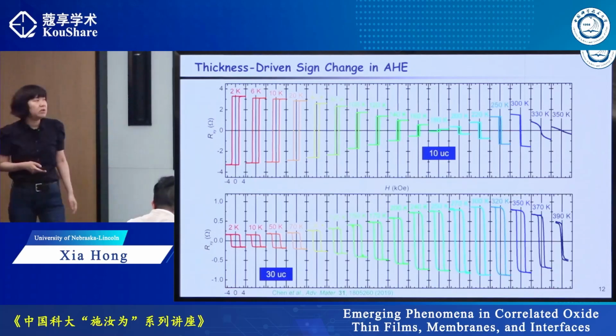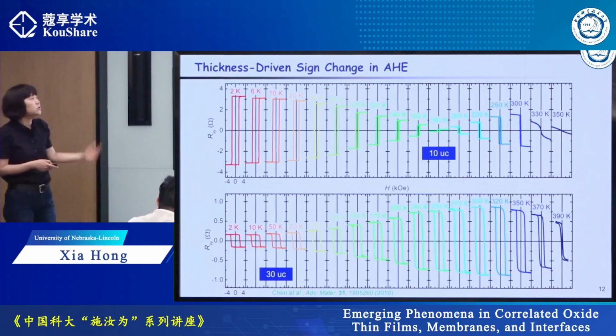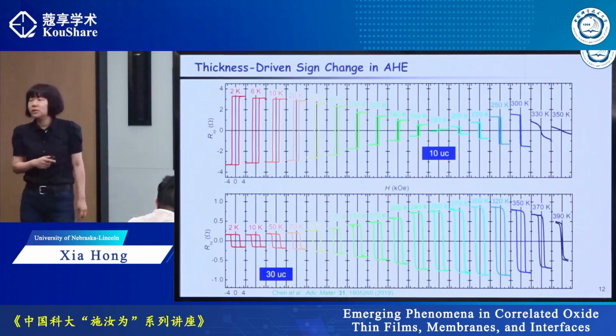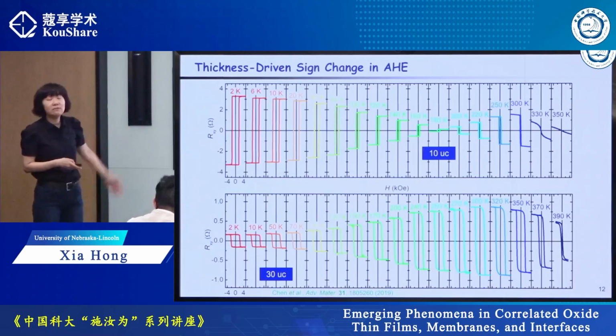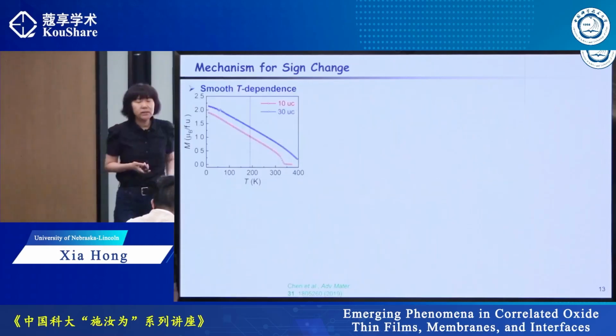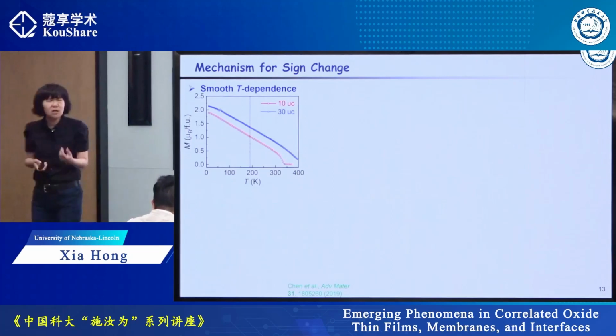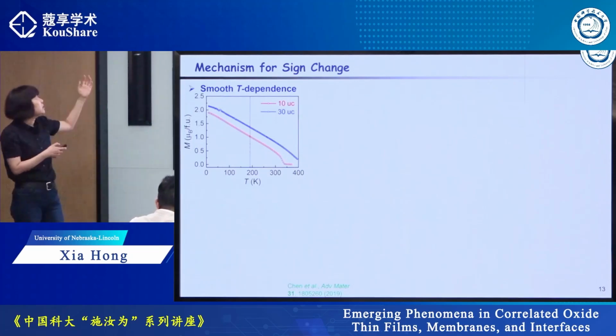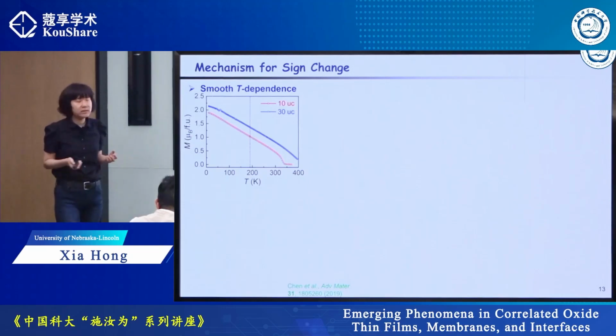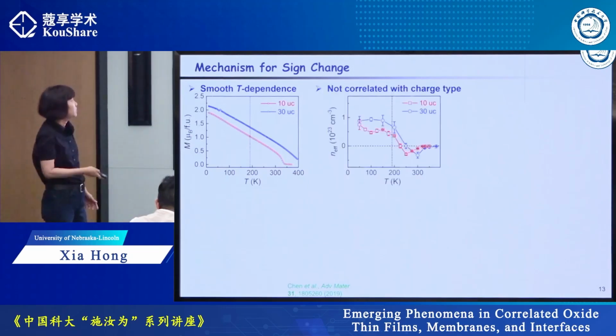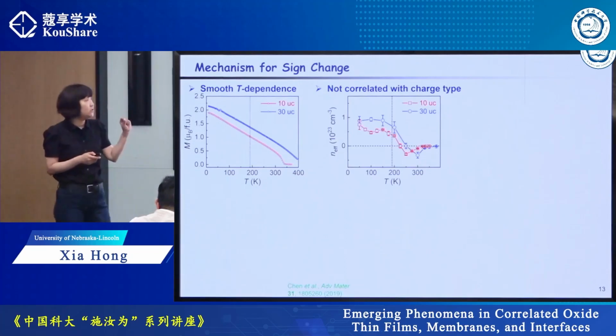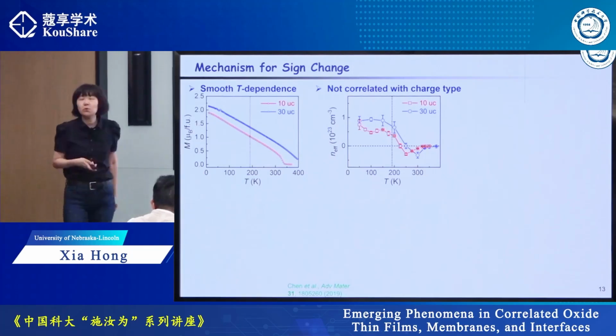Such sign-changing anomalous Hall effect actually can be tuned by not only temperature, but also film thickness. Here we work with a slightly thicker film. We still have this non-monotonic temperature dependence, but this time I do not have sign change. So the question is what causes this very unusual behavior? Because if you just look at magnetization, apparently at 190 K, there's nothing happening for this film. It's not because I have actually changed over carrier type. I know that if I change from electron to hole, it should have a sign change, but here apparently it is in the hole state.